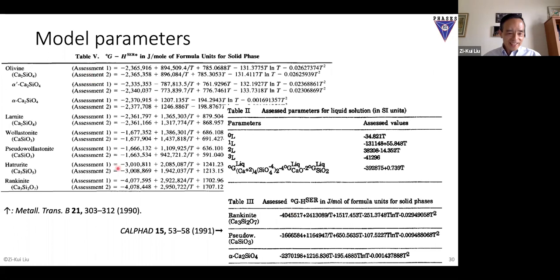And you see that in 1990, they could not decide which model is better. They have 2 models here. And in 1991, they remodeled it, same group. It's actually my professor, Marcelo. And they changed the Rankinite phase, because they found it should do better. Actually, they changed all the phases, these 3 phases, because they found they need to improve it. They're just 1 year apart.